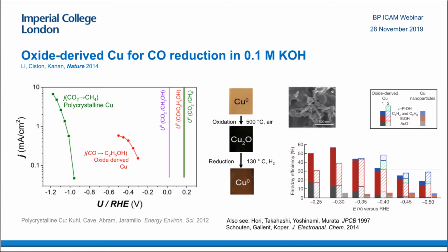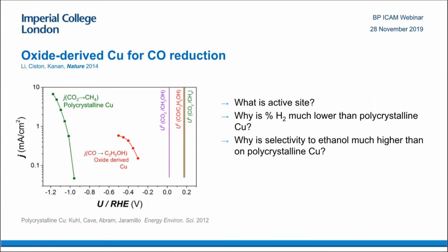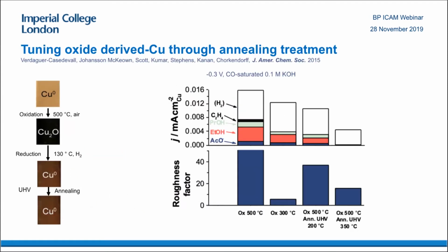Also, the potential loss is a lot lower on this surface, mainly because we're looking at alkaline systems rather than a neutral solution where you'd normally test polycrystalline copper. So we were very interested in this. We were very interested to know what is the active site on this oxide-derived copper. Why has it got lower selectivity to hydrogen evolution than polycrystalline copper? And why does it make a lot more ethanol than polycrystalline copper?